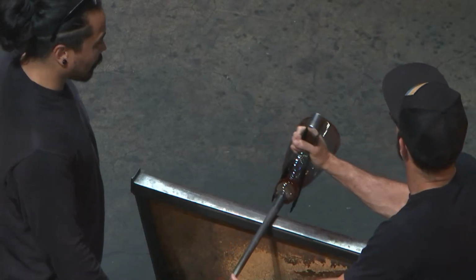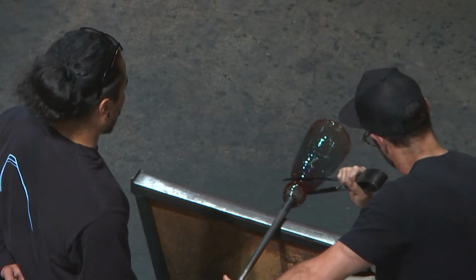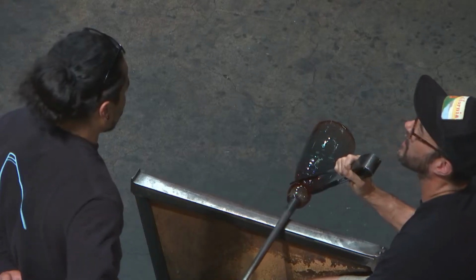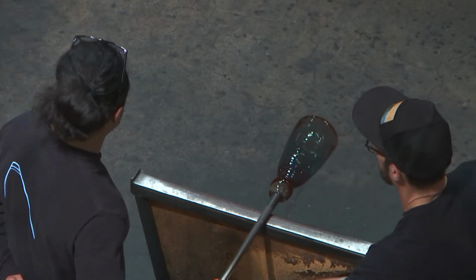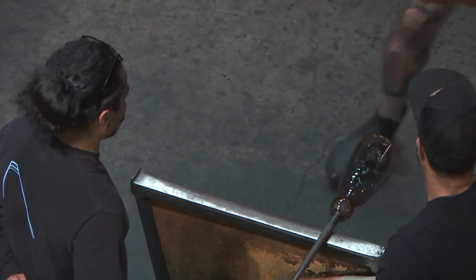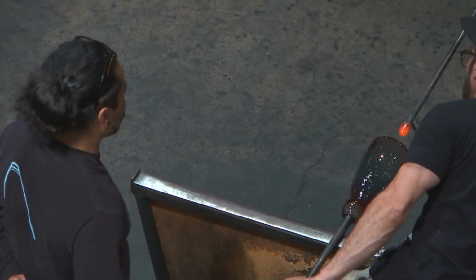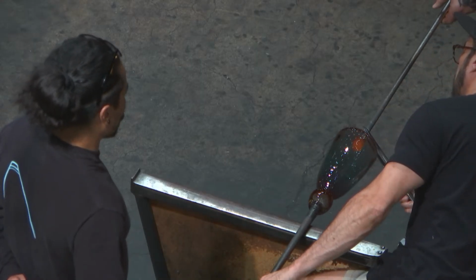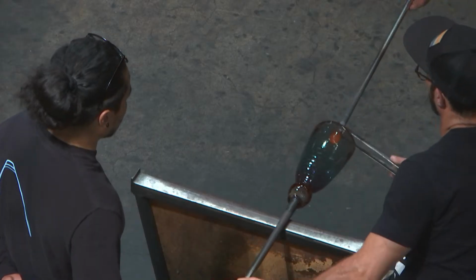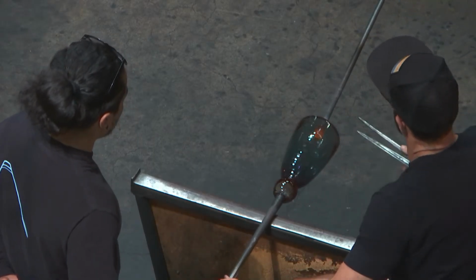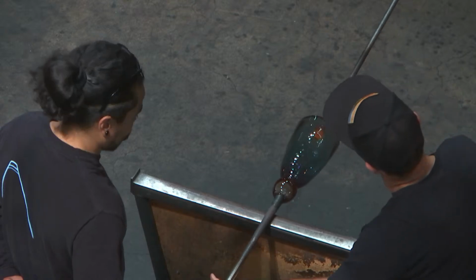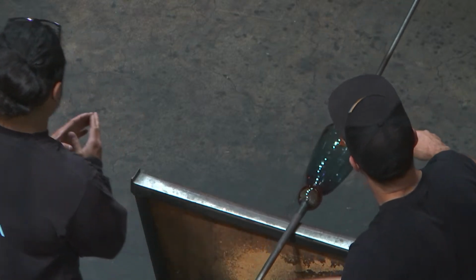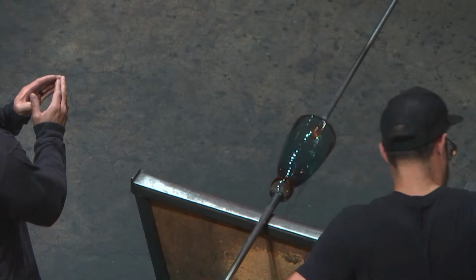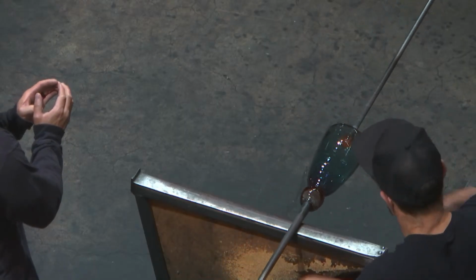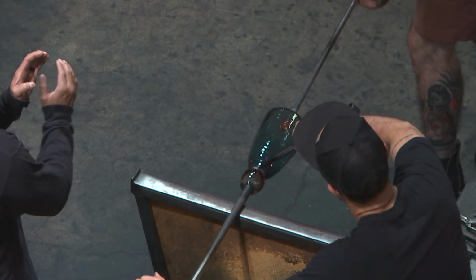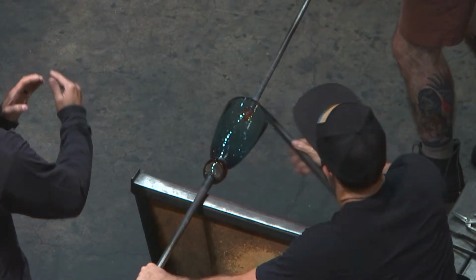Hot glass will stick to other hot glass. So we're going to attach that to the bottom of our piece. Once it's attached, then we can remove it from the blowpipe and work on the other side. So at the right temperature, the glass is hot enough that if you put water on it, it cracks. They're going to put water on that restriction line they carved in right off the head of the pipe. That'll make a weak spot so that when they tap the pipe with a metal tool, the vibrations go into that weak spot and it breaks right where they tell it to with the water right there. They'll break it off the pipe, and Alex will catch it attached to the punty.